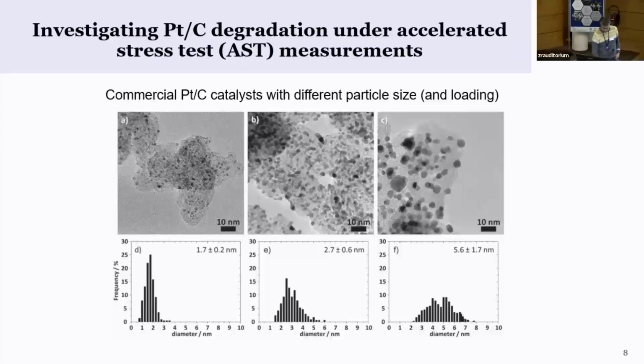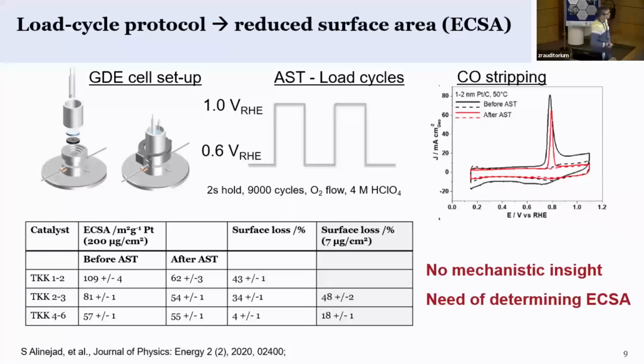And these catalysts, you can, in a specific device where you just look at one electrode reaction, expose, so these are the 3 catalysts, to the stress test, where you just jump up and down and have an oxygen flow, so that you have reaction, and look at the electrochemical surface area, so the platinum surface area, before the stress test and after the stress test.